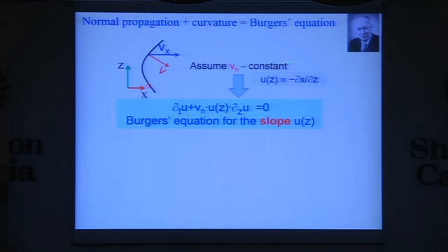For this we're going to use Mr. Burgers. So we're going to derive a Burgers equation here in 2 seconds. Once a microbranch starts, or once a crack front meets any inclusion, it's going to curve the crack front. Now let's assume that the normal velocity is constant. Geometrically, if we take the instantaneous slope of the front profile, under this assumption we can derive a nonlinear equation for the propagation of the front. And this is a piece of a Burgers equation.